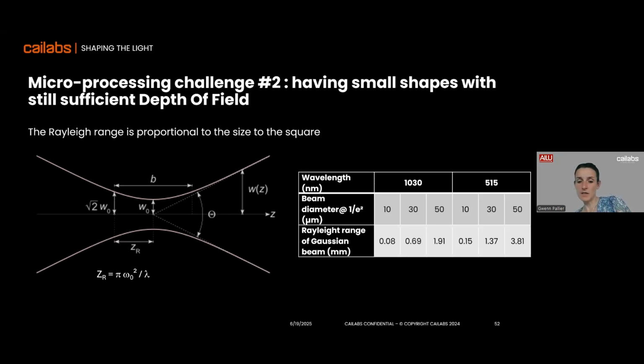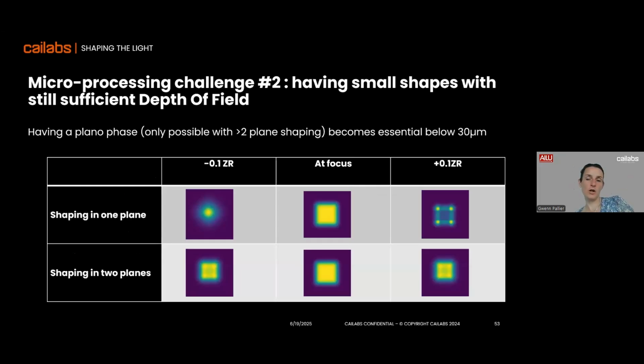And the thing is, if you don't pay attention to the phase of your shaped beam, you can really have, in the end, a depth of field which is way smaller compared to the Gaussian beam. So in our opinion, the conclusion we had at Cailabs is that you cannot only shape the intensity profile, you have to shape also the phase profile. To do that, you need to have at least two planes.